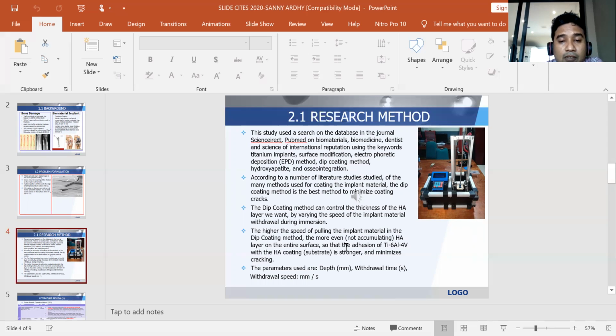The higher the speed of pulling the implant material in the dip coating method, the more even and non-accumulating the hydroxyapatite layer on the entire surface, so that the addition of Ti-6Al-4V with hydroxyapatite coating is stronger and minimizes cracking. The parameters used are depth in millimeters, withdrawal time in seconds, and withdrawal speed in millimeters per second.